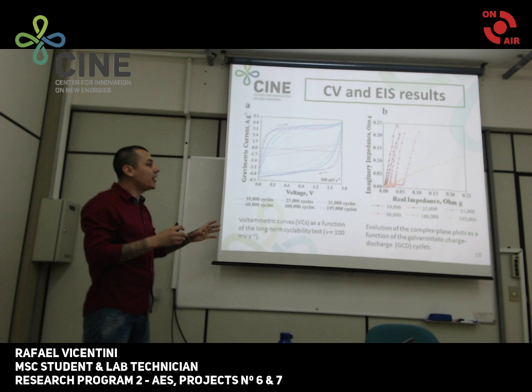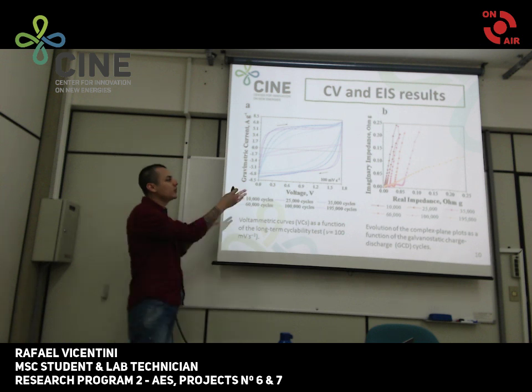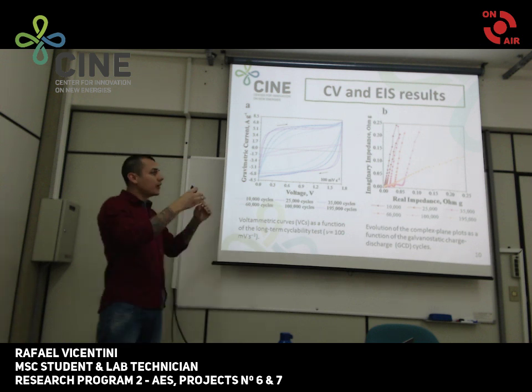And in both cases, the cyclic voltammetry and the complex plane plot, even after more than 100,000 cycles, have a very, very good shape.